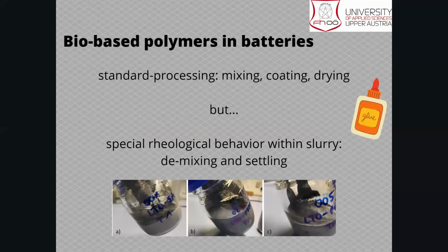So what you can do with your sodium alginate, you can in principle do the same standard processing as you do with a classical solvent-based battery electrode. So you do these mixing steps just within water as a solvent, you do a coating, and afterwards you evaporate your water. Nevertheless, what we found out is that we do have a special rheological behavior within the slurry.